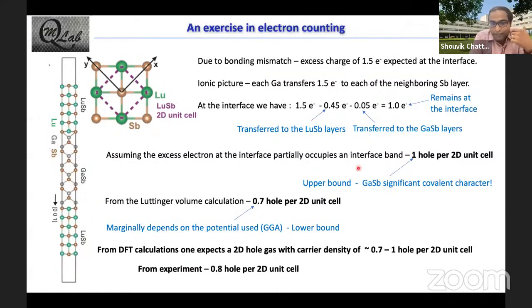So now if it occupies an interfacial band, you expect 1 hole per 2D unit cell. All right. And of course, this is an upper bound because gallium antimonide has a significant covalent character. So from this exercise, we can put a lower and upper bound, which is between 0.7 and 1. And what we find from experiment is that we have about 0.8 holes per 2D unit cell. Okay, so this matches quite well, but let's take it one step further.